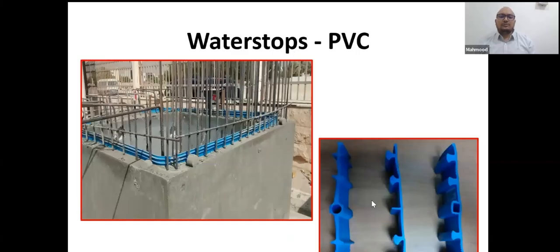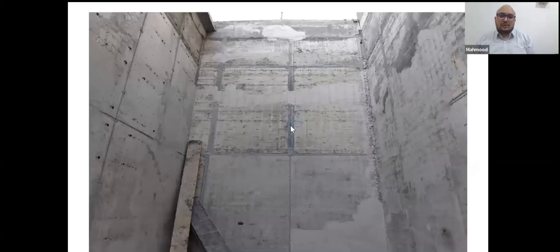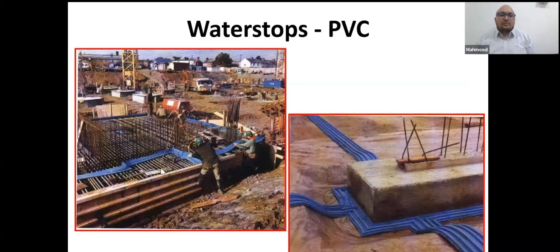There is a PVC water stop. PVC water stop is produced by the extrusion technique. There are various water stops, internal and external water stoppers, for expansion and construction joints. During the concreting, they will fix the PVC water stopper and cast the concrete. You can see the external PVC water stopper is visible. This is the external one to prevent water from the joints. They lay the PVC water stopper according to the layout.